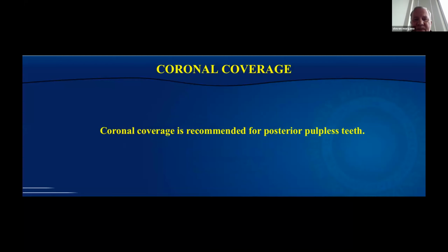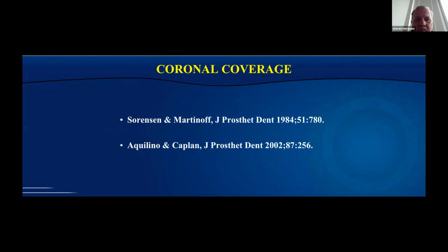Now, coronal coverage. Coronal coverage is recommended for posterior teeth. Is that a myth or is that a reality? Now, if you look at Sorensen's study, it's the same one where they looked at length of posts. They evaluated 1,273 pulpless teeth. And what they found was a posterior pulpless tooth without a restoration that covers the cusps: failure rate was very high, depending on the location in the mouth, anywhere from 40 to almost 50%.